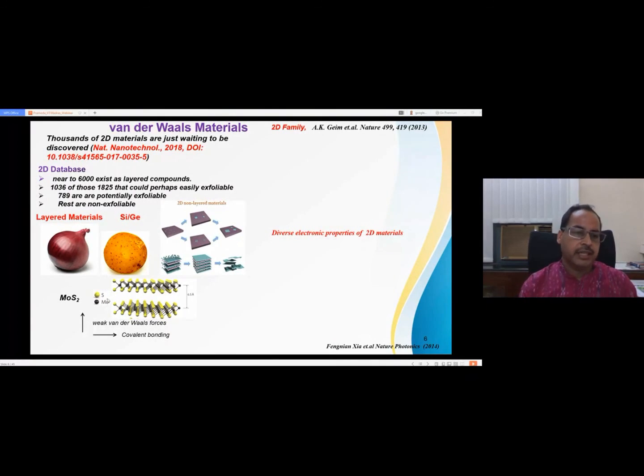Here you can see a typical TMD, molybdenum disulfide. The molybdenum atom is in the middle and these are the sulfur atoms. The in-plane bonding is a covalent bond, a strong bond, but the out-of-plane bonding is van der Waals force. So you can easily cleave layer by layer. If you take a bulk, you can limit it to the monolayer or few-layer limit. In a non-layered material, where there is no layer structure, it is very difficult to go to the single-layer limit.